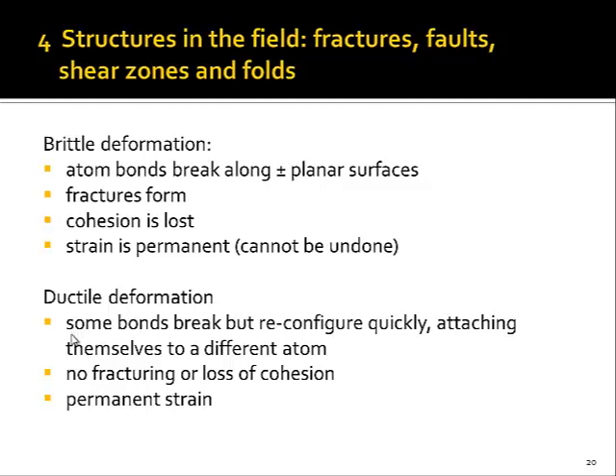Ductile deformation is different in that regard. In ductile deformation, not all bonds, atomic bonds, break along planar or non-planar surface at the same time, but what we see here is a process at crystal and in fact at atom scale, where atom bondings are opening and reconfiguring one by one fairly quickly, so that we never have the situation that along a larger surface area atom bondings are broken. They are snapping and closing quickly enough, and that prevents cohesion to be lost. So bonds between individual atoms can open, but very quickly they get attached to a different atom, and so no large-scale loss of cohesion is occurring. And permanent strain is acquired in such a successive process, in such an evolutionary process that you will see and will learn happens at atom scale within individual crystals, cumulatively changing the shape of rocks.